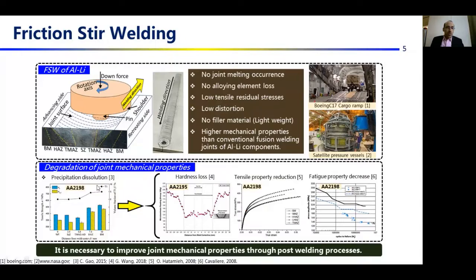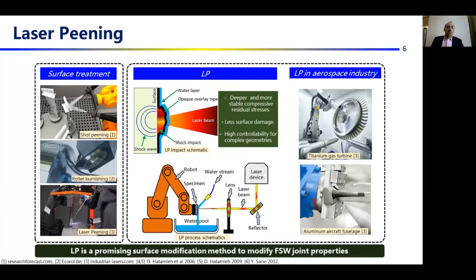However, the dissolution of precipitate phases during the thermomechanical effects of friction stir welding leads to the degradation of joint mechanical properties such as the hardness, tensile strength, and fatigue properties in the joint center. So it's necessary to improve the joint mechanical properties by post-welding processes.